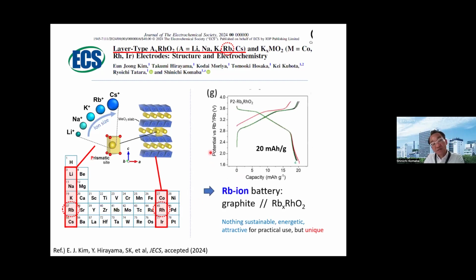And the electrochemistry is here. As you can see, it is a very beautiful charge-discharge curve in the rubidium half cell, but the reversible capacity is so limited. This means that by combining graphite and rhodium oxide, we can assemble a rubidium-ion battery. But please note that it is not sustainable, has little energy storage, and is not attractive for practical use, but I believe it is unique in terms of science.